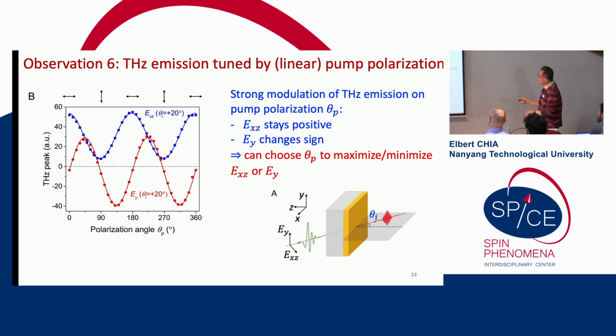And you can see here that EXZ stays positive, but the modulation is quite large. Whereas EY has not just a very large modulation, but we can actually change the sign of the polarity of the terahertz pulse. And so in principle, we can choose theta P to maximize or minimize the different components of the emitted terahertz pulse. For example, if I were to choose 90 degrees here, you can see that the total terahertz intensity is very small.